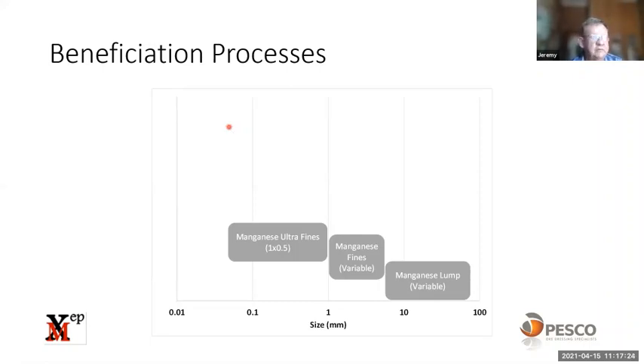So now that we've covered the basic fundamental characterization of the ore types, you're going to go more into the beneficiation processes. And if we look at manganese, what we find is that there's different size ranges. So we have lump, and the size range is variable. It depends upon your ore body. It can be anything from a 75 mil top size down to a 30 mil top size, and the bottom size can vary between 8 and 20, but we have a lump fraction. We also have a fines fraction. And then we will have an ultrafines fraction, which would be typically the -1.